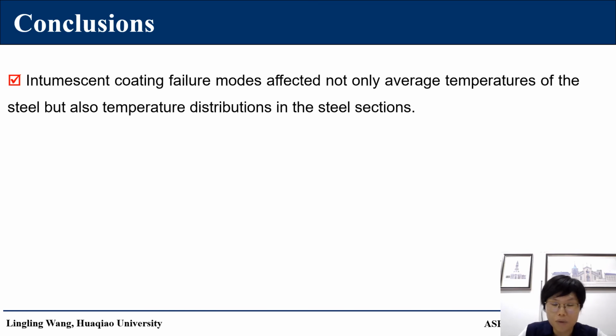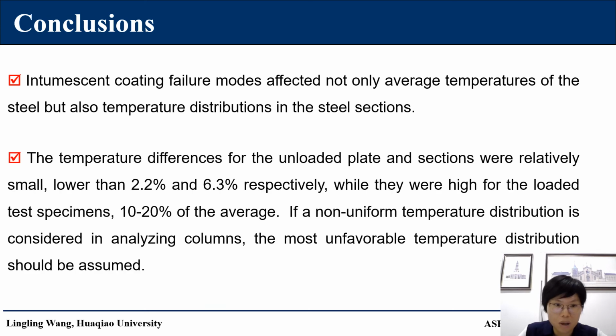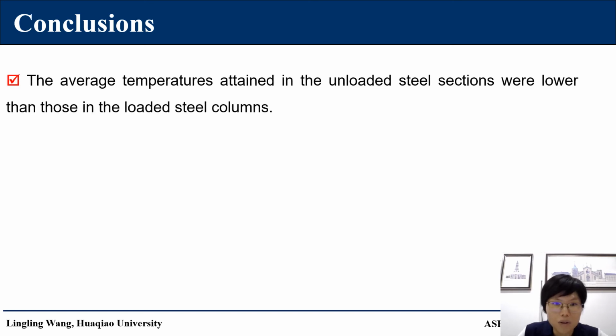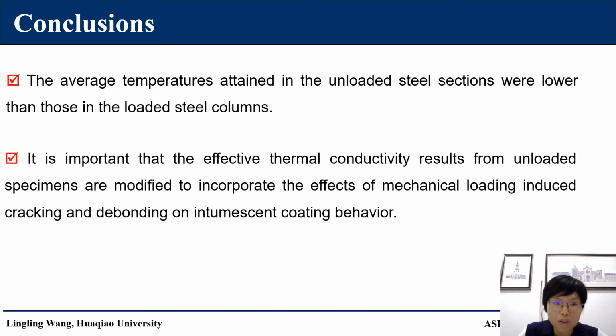Intumescent coating failure modes affected not only average temperatures, but also temperature distributions. The temperature differences for the unloaded plate and sections were relatively small, while they were high for the loaded test specimens. The average temperatures in the unloaded steel sections were lower than those in the loaded steel columns. It is important that the effective thermal conductivity results from unloaded specimens are modified to incorporate the effects of cracking and debonding on intumescent coating behavior.